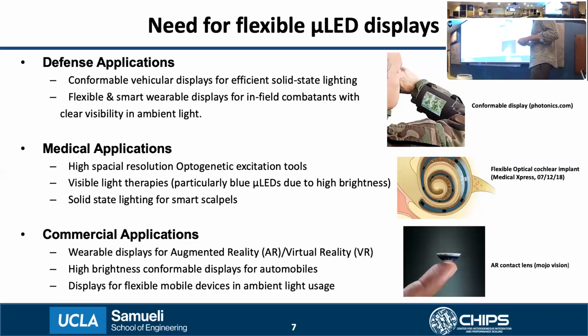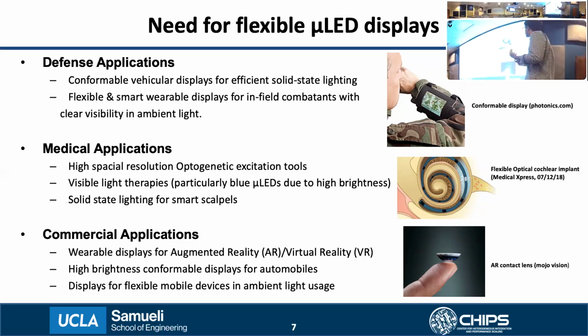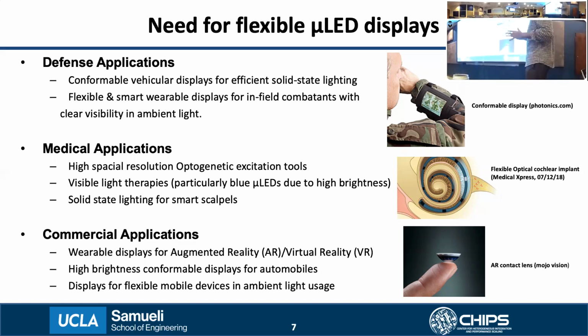So the gallium nitride is a very stable crystalline material. It's generally non-toxic. So when blue or UV LEDs are used to stimulate the cells, the way optogenetics is done is you genetically modify the animal in such a way that certain ion channels become light sensitive. But you can control what frequency of light actually opens or closes that particular ion channel. So if blue LEDs using gallium nitride are used, it's typically safe because the material is very stable and biocompatible.